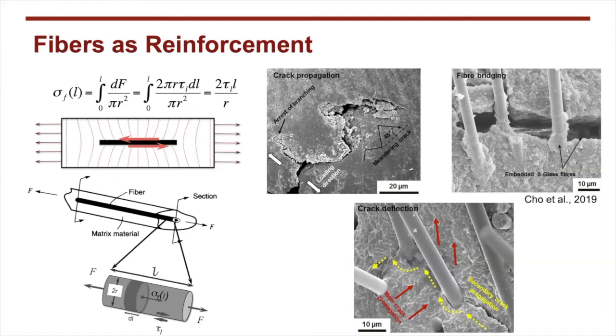From a practical point of view, there is a limit to which we can mix fibers into a paste, because the higher the amount of fibers that we add to any slurry, the greater is the viscosity, and then the lower is the workability of the composite. The second reflection to make here is that we need also to increase the strength at the fiber matrix interface. If the shear strength here is low or the bonding is poor, we have fiber debonding, which clearly decreases the strength of the composite.